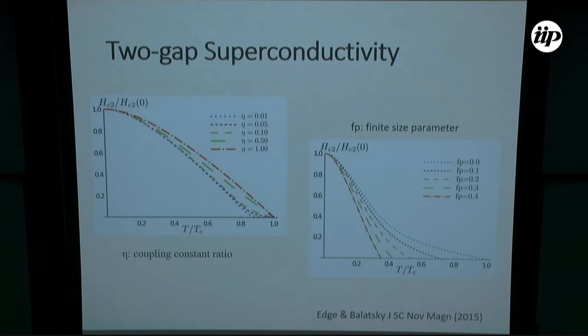what has been analyzed in the comparison with what we should expect for a two-gap superconductor. This has been predicted and studied by Edge and Balatsky recently for the SrTiO3 system and the SrTiO3/LaAlO3 interface, for a set of different parameters, for the coupling parameters, for the size of the interface, and so on. One of the signatures of the presence of two gaps should be this positive curvature of HC as a function of temperature. But we don't see that for all the dopings.